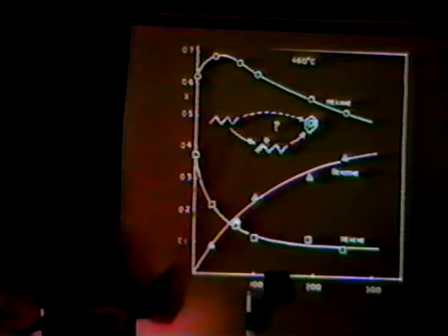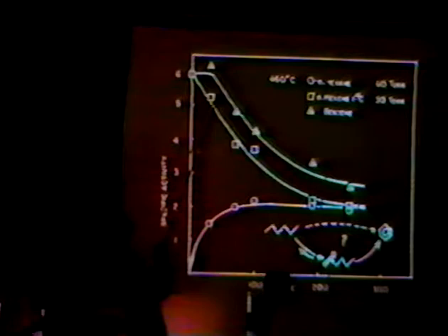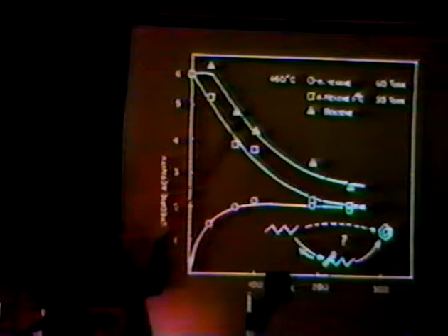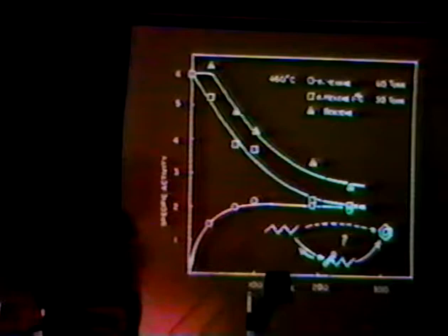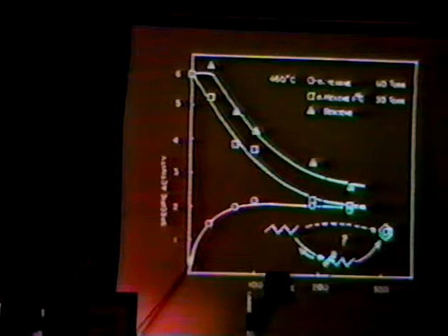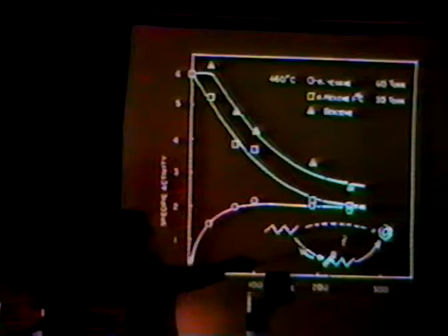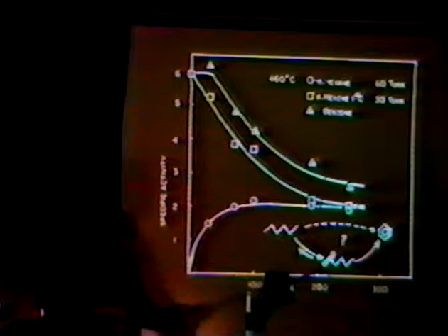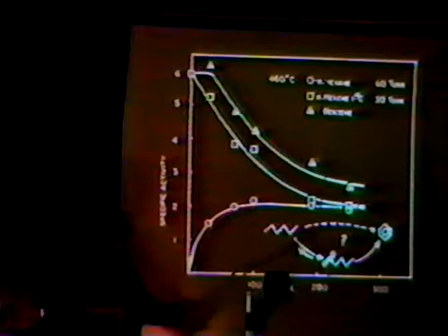The results show that the benzene (solid triangles) and the hexene have almost the same radioactivity — in fact, benzene has slightly higher specific activity. The non-radioactive hexane also begins with zero radioactivity and comes up. All of these pairs will come together at infinite time. It looks like we do indeed have rapid equilibration between hexane and hexene, and then hexene goes on downstream. We do not have direct interconversion from hexane to benzene bypassing gas-phase hexene.